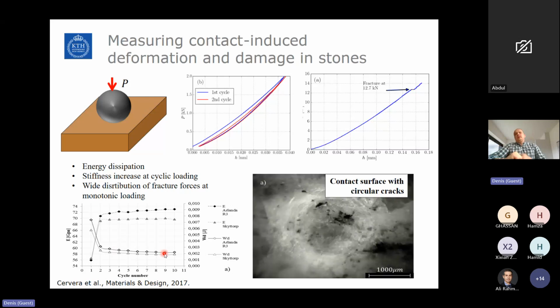We also did monotonically increasing loading tests where we apply load and keep increasing the load until the material responds with fracture. What we see experimentally are jumps in force displacement curves like that, and those jumps are also accompanied by acoustic emission. After those jumps, we cannot see too much at the stone surface. We see a certain amount of ring cracks, so-called Hertzian cracks, on the stone surface, but those ring cracks cannot be responsible for the jumps. So the hypothesis was that it's mostly due to median cracks propagating under the indenter downwards in the specimen. And those cracks can actually fracture the stone completely.